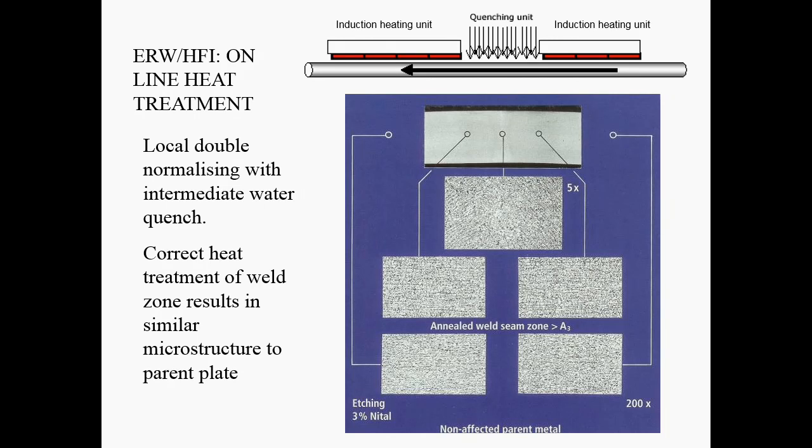And what they do is they heat the surface of the steel up to about 900 degrees C, and the bulk temperature gets to about 850, 900. And then they allow it to cool in air. And that gives you a relatively small grain size of the standard thermodynamically stable structure of that steel, so ferrite and pearlite.